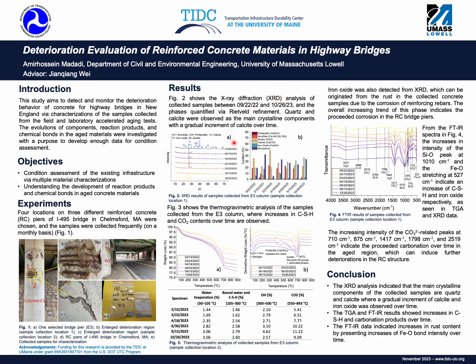Based on the XRD pattern and the quantification analysis based on Rietveld refinement, it can be seen that quartz and calcite, or calcium carbonate, are the main crystalline components of the samples, where we can also see a gradual increase in calcite over time, which can be seen in the quantification analysis shown in part B of this figure 2. Also, from this XRD result, we can detect iron oxide as another phase, and it is likely a result of rust in the collected samples, which is due to the corrosion of reinforcing rebars. The overall increase of this phase also suggests an ongoing corrosion in the reinforced concrete bridge piers.